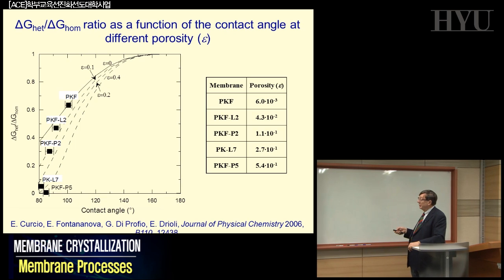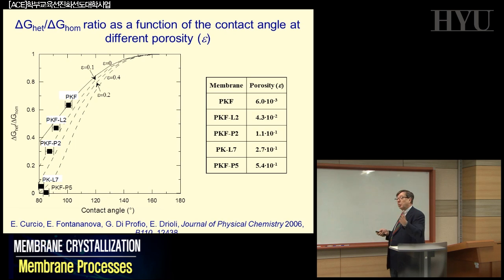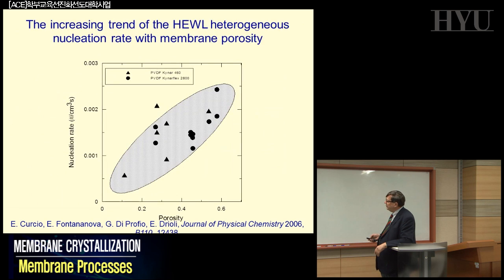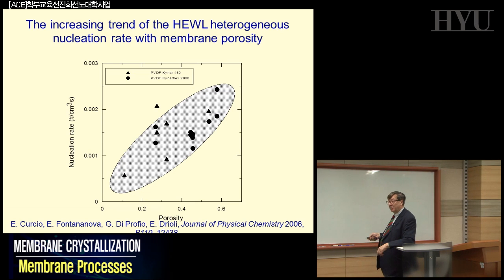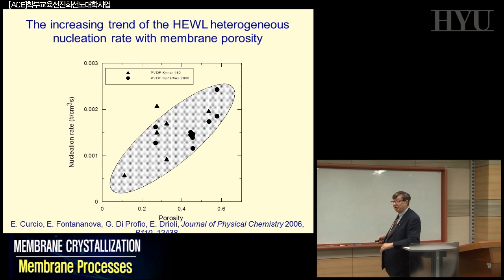So what is important at the moment is to understand that we are not only evaporating and doing what can be done just by warming up your solution, but we are introducing new parameters that can have an effect on the delta G heterogeneous and delta G homogeneous, and can have an effect on the kinetic of crystal growth, for example, and on the other important parameter. And experimentally, the nucleation rate is the most important parameter we have to keep under control. In terms of the porosity, it is not very simple; these are just a protein that you can try to crystallize, but basically the trend is quite interesting and just the one that we were anticipating before. And that is again data that now in physical chemistry are well understood and well published in the literature, you can find them.